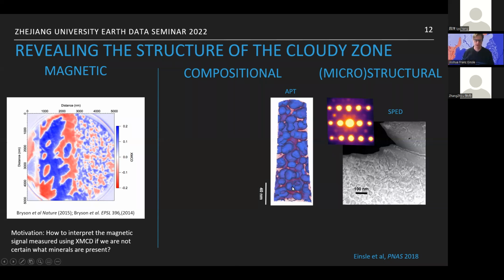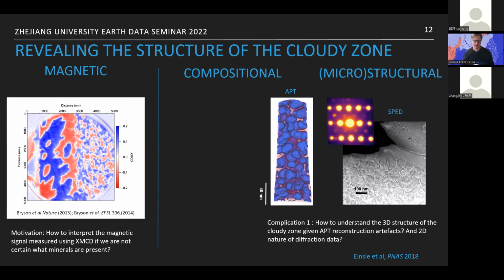It was very informative, but it was slightly flawed in the sense that the shapes of these grains are not quite realistic. There's a lot of assumptions that go into the reconstruction, and the composition was coming in a bit richer in iron in the matrix than we were expecting. Likewise, we tried doing an electron diffraction technique, but this is largely 2-dimensional, and we have a complex 3-dimensional structure. So if we have these, how do we get these data sets to make sense?